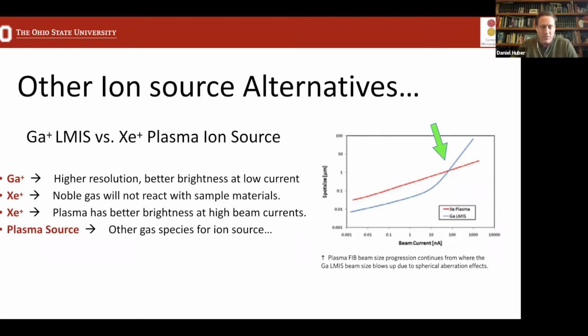Gallium can react with your sample. You can embed gallium into your material. It can have some negative effects and some changes that you need to be mindful of. So there are some other ions, like xenon, which are very good. Xenon plasma sources are very good at high currents. At very high currents, they maintain a small effective source, so they give you high brightness at very high beam currents. However, at lower beam currents for making TEM foils and such, the gallium liquid metal ion source gives you a little bit smaller effective ion source.